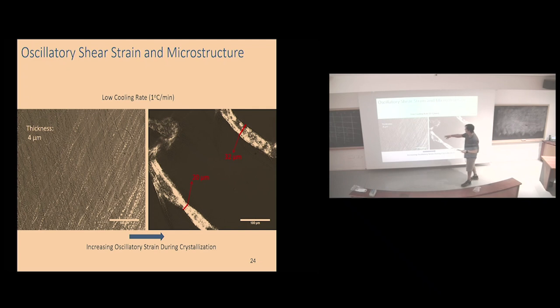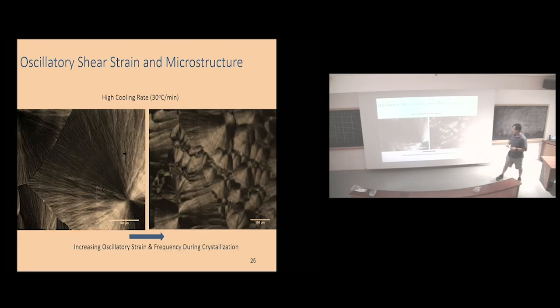So we have the static one, and then you saw before where we make these bundles of fibers which can be 20, 30 microns in size. And what about this? The cooling rates and high cooling rates and increasing oscillatory shear. So we're at 30 degrees per minute, and we have this under very low shear rates or no shear rates, we get these monsters. I mean, this is 100 microns. So you can see this with the eye. This is how big these things are.